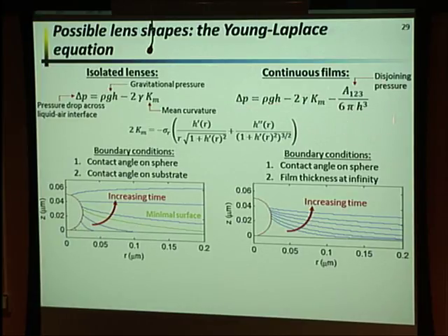We're adding in another term here, and this is a disjoining pressure. This becomes important when you have very thin films. So you notice this H is the thickness of the film. When this H gets around the 10 nanometer level, this term starts to become significant. So really, everything on this side is you're adding up different force terms. And it's okay to add different force terms if those terms are significant. So you have to make sure you're capturing everything that's significant.